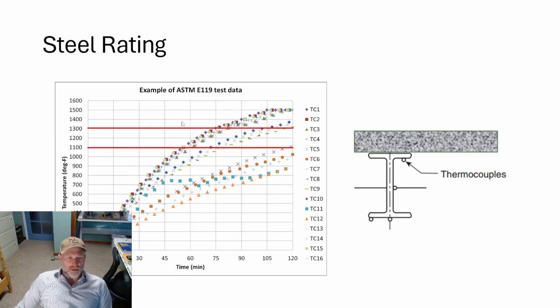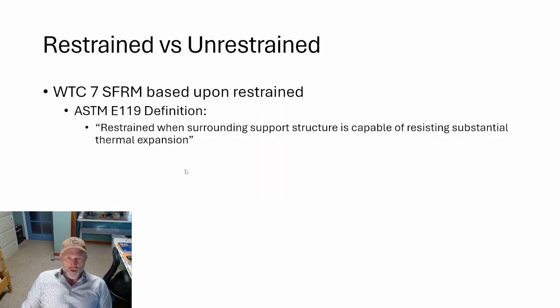So just take away from this discussion, this is how it works. Normally steel in that kind of a configuration would fail down around here. It would fail in 8 minutes. Very fast failure because of the temperature induced within the standard fire. But because of the thermal resistance of the applied fire resistant material, it's sprayed on insulation, the cementitious type insulation, it delays heat transfer longer. It's basically insulation, and that's what gives you your 1 hour rating.